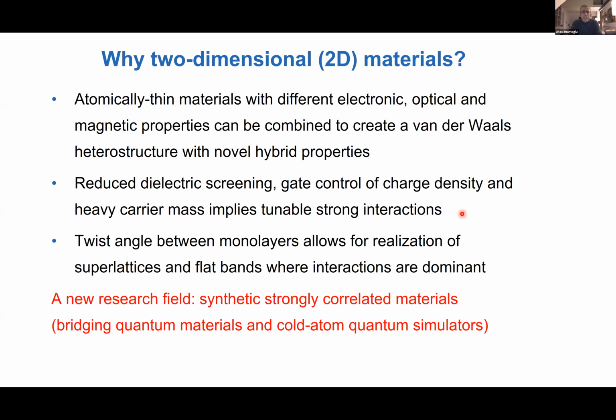Now, there is an additional, really amazing degree of freedom in this material. That is, when one stacks these materials to form this van der Waals heterostructure, one can also introduce the twist angle. And this results in the appearance of a superlattice, a moire superlattice, which can exhibit flat bands. And in that case, the interactions become the dominant energy scale, and one can explore interesting, strongly correlated phenomena.